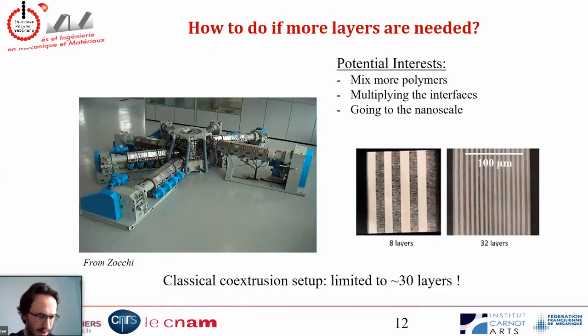So now I explained how to make 3 or 5 or maybe 9 layers, and I want to switch to real multi-layers, so say 1,000 layers. How can I do that? You saw previously that with 2 extruders I can make 3 layers, with 3 extruders I can make 5 layers. So if I add more extruders, I can make maybe 10, 20, or 30 layers. But of course, at some point, I can't add more extruders in the system. So I will be maybe limited to 30 layers.